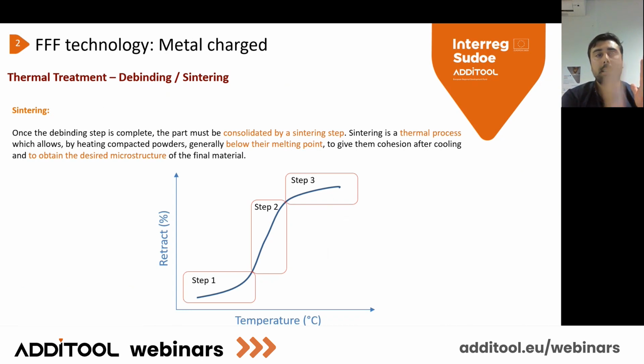And then at the last step, we have the sintering. Once the debinding step is complete, the part must be consolidated with a sintering step. It's a thermal process, and when we heat compacted powders, it's important to stay below the melting point. The sintering gives them cohesion after cooling to obtain the desired microstructure of the final material. So we have a raise of temperature, a maintain, and then a decrease.